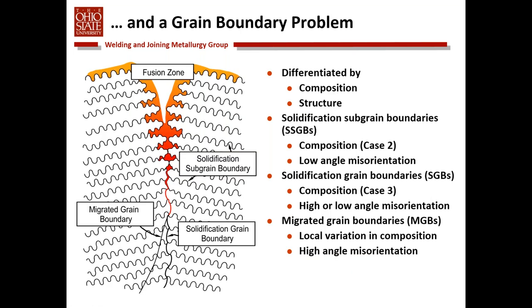It's also a grain boundary problem. So the interesting thing about cracking in welds, virtually all cracking that occurs in welds other than some forms of hydrogen-induced cracking, is that cracking occurs along grain boundaries. This is an example of a grain boundary forming in the fusion zone where we have a solidification grain boundary where groups of cells or dendrites come together to form that boundary, something called a migrated grain boundary that is a crystallographic boundary that pulls away from that solidification grain boundary. We'll see that this migrated grain boundary becomes the site of what's called ductility dip cracking in a lot of materials. There's a lot of detail. We've done a lot of studying of microstructure and solidification behavior in welds. If you refer back to my textbook on welding metallurgy and weldability, you can find a lot more detail there regarding the metallurgical development of these boundaries.